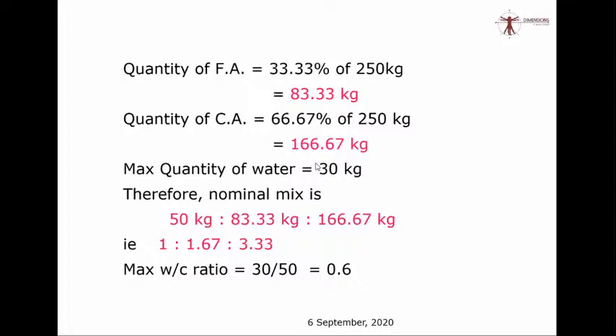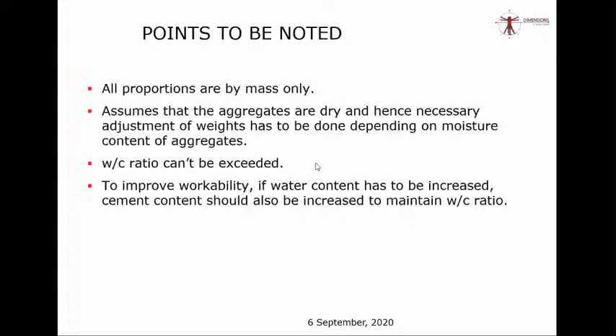Those of you who have had interactions with site engineers would have got this feedback that for M20 concrete, we roughly use 420 to 425 kg of cement per m cube, whereas the minimum requirement is only 300 kg. So these points are to be noted here. All these proportions mentioned by IS 456 are by mass.